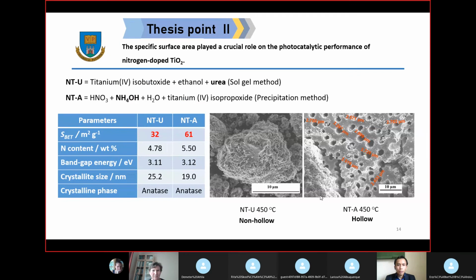Our second thesis point is that the specific surface area plays a crucial role in the photocatalytic performance of titanium dioxide. We prepared another nitrogen doped titanium dioxide with a different method and a different nitrogen source, and then we compared both catalysts. From this figure, we see that the N-TiO2 catalyst, prepared with the sol gel method, produced a non-hollow structure. However, the NTA produced a hollow structure. This morphology really correlates with the specific surface area: with the non-hollow structure, N-TiO2 has a lower specific surface area compared to the NTA catalyst, even though both of them are in the anatase phase.